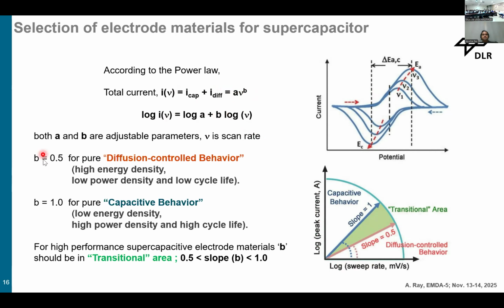If the b value is exactly 0.5, then the material shows diffusion-controlled behavior, that is, a redox reaction occurs. This gives a high energy density but low power density and low cycle life. But if you get a b value of 1, this is the ideal capacitive behavior, and 0.5 is ideal for batteries. So capacitive behavior for 1 gives low energy density but high power density and high cycle life. So you can see this is the capacitive zone and this is the diffusion control zone.